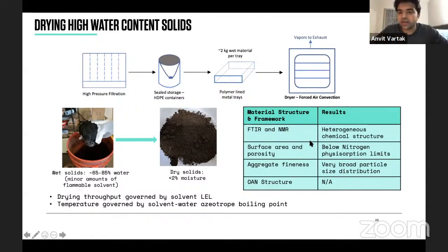The surface area and porosity. It's a technique called nitrogen physisorption, wherein the nitrogen goes into your small particle, and depending on how much nitrogen went in, you quantify that, and you know if your particle is a solid particle or if it made those channels that I'd shown in one of the pictures.